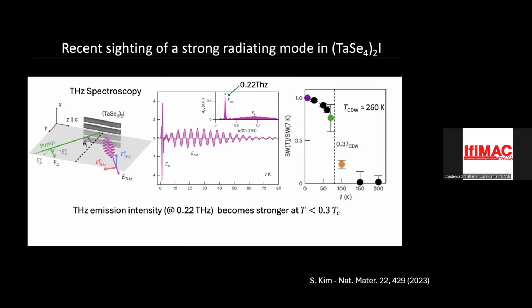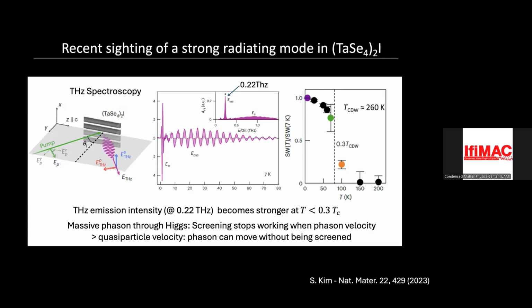The reason you have the sharp rise at a temperature very far from the CDW transition is because at this temperature, the phason velocity becomes much faster than the quasiparticle velocity, and screening is not good enough. And so basically the mass comes from poor screening, and there are two contributions to screening. One is the number of quasi-particle excitations you have, which is already very small because this is a very good insulator. And the other is how fast can they move to screen. And basically there's a conspiracy between these such that at 0.3 T_C, the screening becomes very, very bad. And suddenly you see this massive phase mode emerging. So that is their experimental observation, and that's their proposal for what this is.